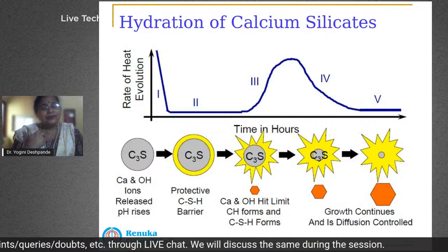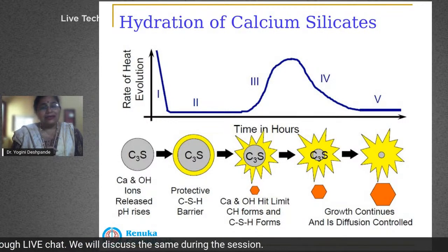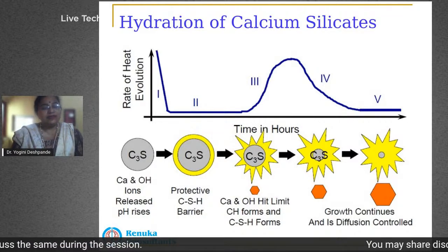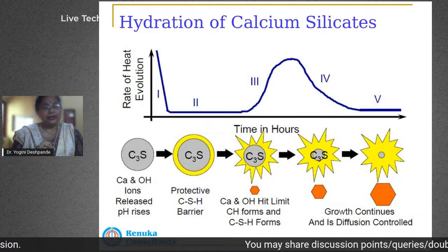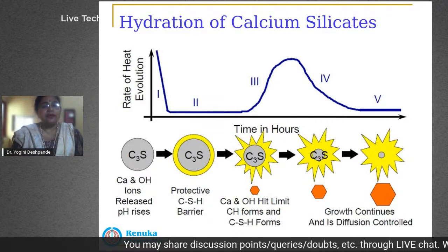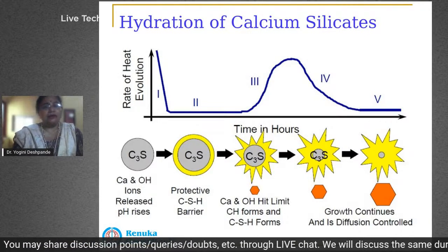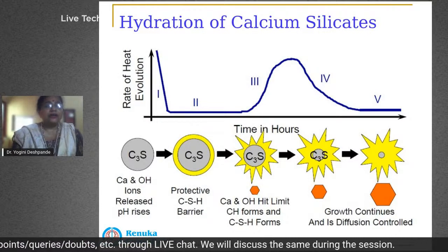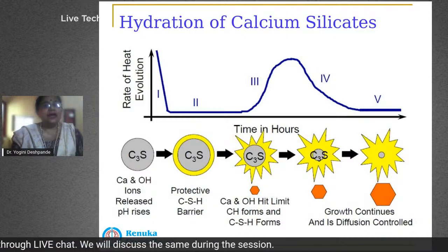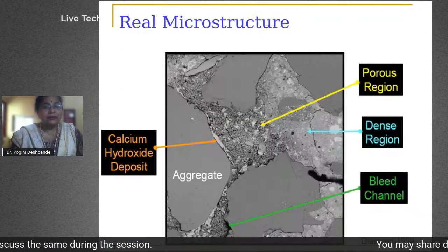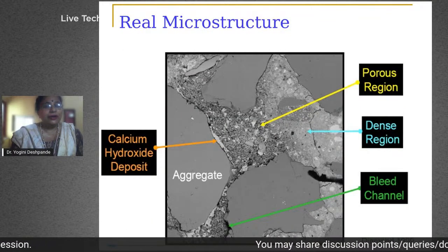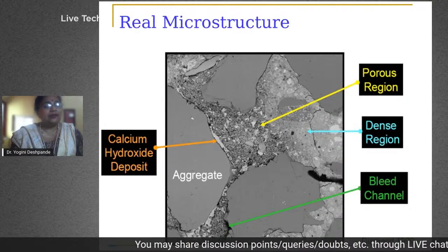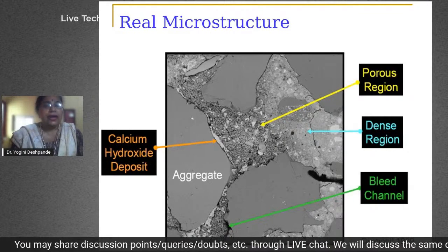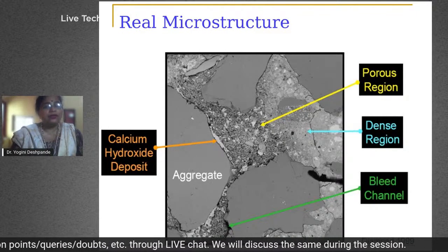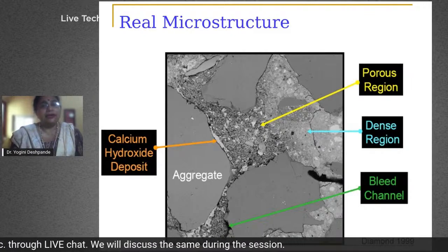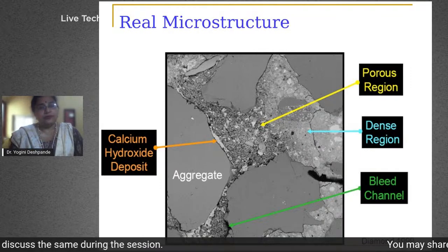The cement hydration process is similar - the hydrate product forms all around the cement particle, and that chemical reaction continues, with the cement particle continuing to get smaller, so that after 24 or 36 hours, the particle has grown very small in size while the hydration product has increased in size. That is what you are seeing here - the small white particles are the small cement particles left behind, and the grayer particles are where the cement is fairly or almost completely hydrated, to either CSH or CH.